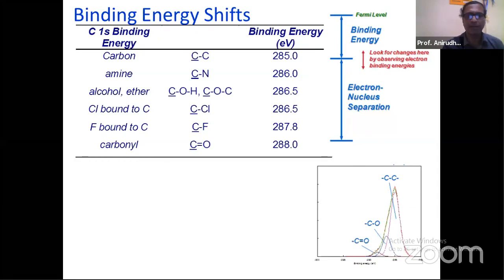So when it is pure carbon, carbon-carbon bonding, the 1s binding energy for carbon has been found by many investigators to be 285.0 electron volts. Whereas when carbon bonds with nitrogen, CN bonds, people have done investigations using XPS. They have synthesized those compounds and done enough experiments to confirm that when carbon bonds with nitrogen, the 1s electrons from such a system involving a CN bond belong to a binding energy of 286.0 electron volts. Similarly, for C-OH coordination or for C-O-C, the carbon 1s binding energy was found to be 286.5, and many other values are also given.